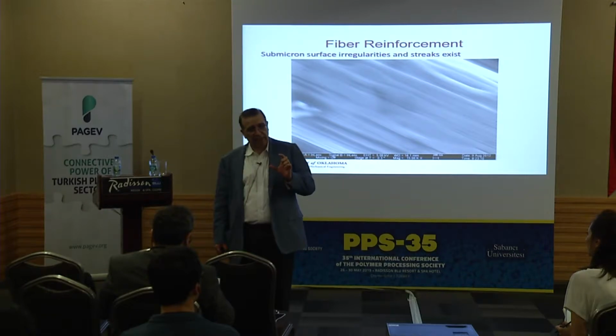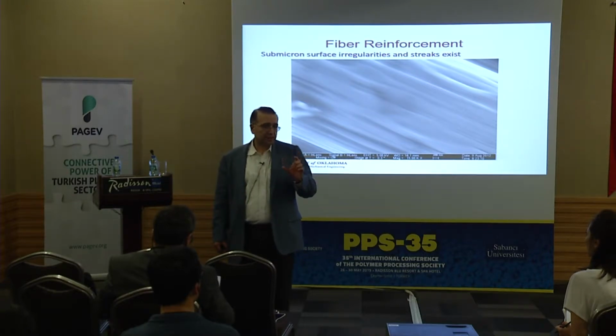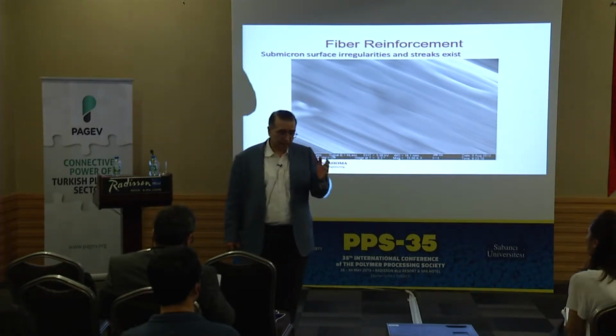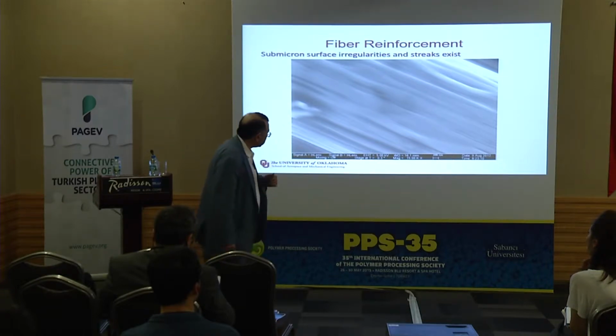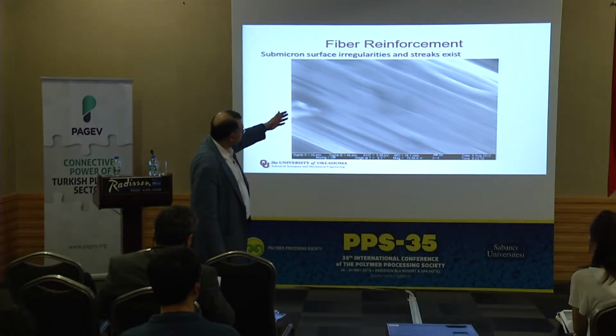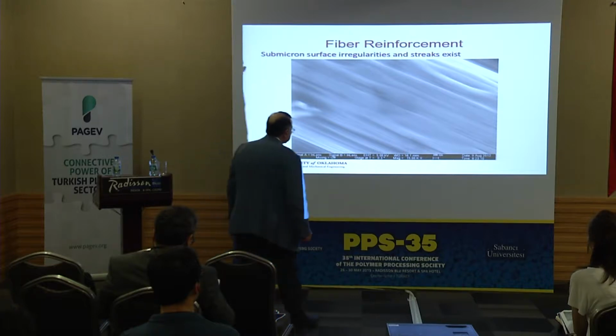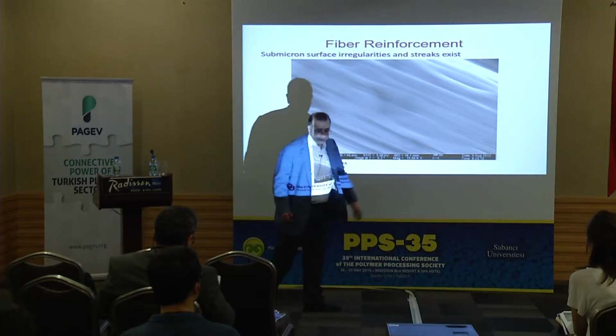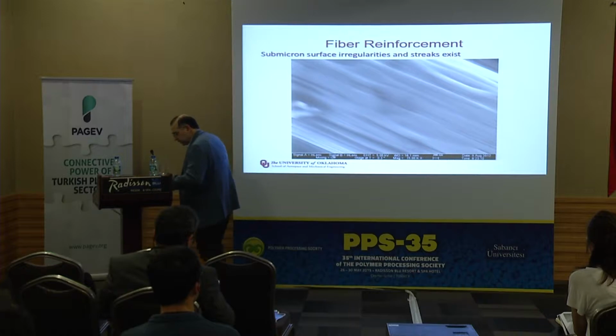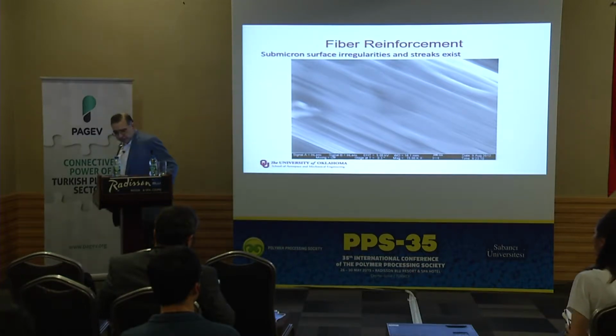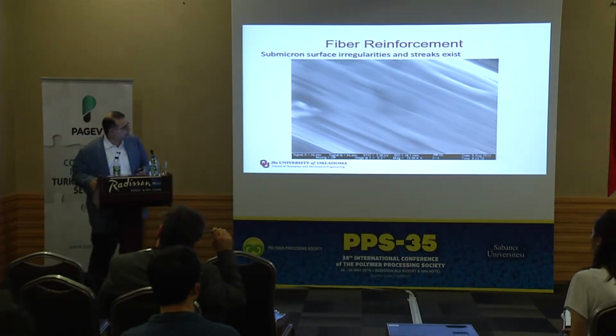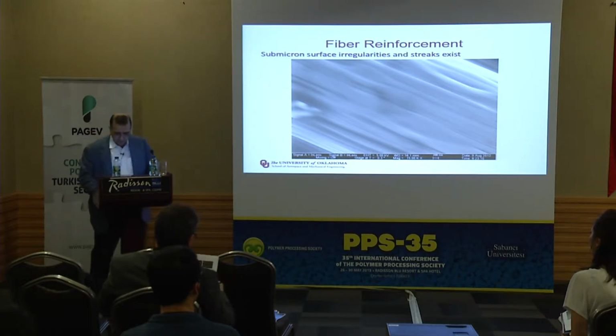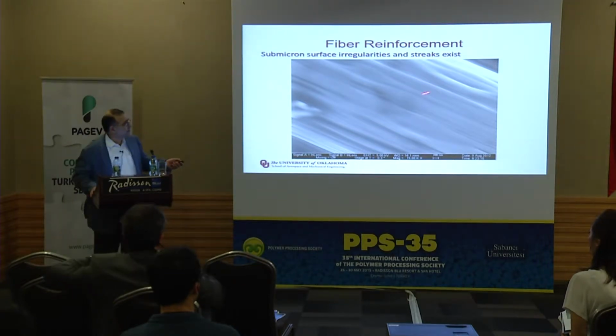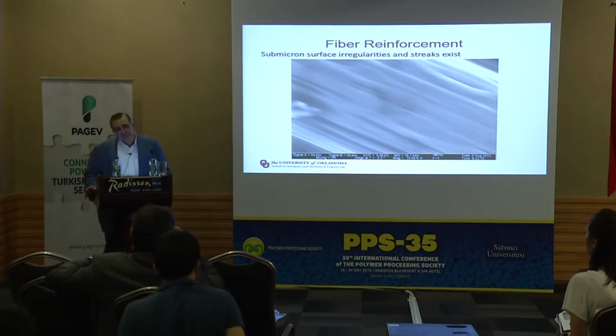Usually, this layer is to create an improved interface with the resin. Okay? So you will have nice bonding, chemical bonding, covalent bonding with maybe the epoxy. So these sizings on the surface, companies do not really disclose the chemistry, but these are silane-based sizings, and there is some literature on that. You can get rid of this sizing by heat treatment.